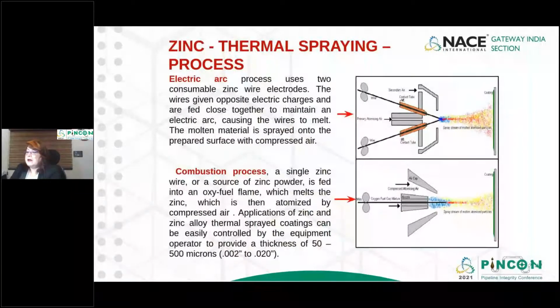Electric arc spraying feeds two electrically oppositely charged zinc metal wires towards each other and produces an electric arc at the point just before the two meet. As the arc melts the metal wires, high pressure air is used to spray fine droplets onto the properly cleaned and prepared metal surface, whereas in the combustion process a single zinc wire or a source of zinc powder is fed into an oxy-fuel flame which melts the zinc, which is then atomized by compressed air.